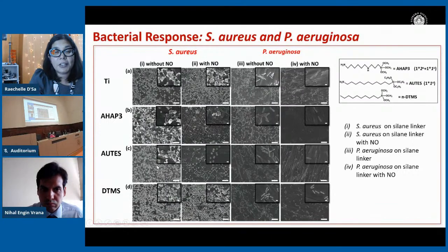For the AHAP and AUTES surfaces, you can see that before nitric oxide has been tethered onto the surface, you see lots of bacteria adhered, and after the nitric oxide has been immobilized onto the surfaces, you can now see that we have in fact been able to kill Staphylococcus aureus on the surface. The same trend is also observed for the gram-negative bacteria Pseudomonas aeruginosa, where both our nitric oxide silanes have been able to effectively kill off the bacteria.